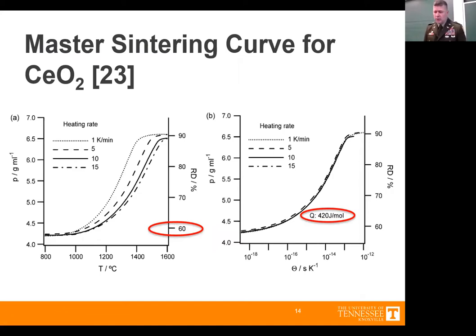There's actually some literature that shows that the master sintering curve method does work reasonably well for cerium dioxide. However, I want to call your attention to two things on this slide, and then we'll compare and contrast those with my own results later. This work starts out at approximately 60% theoretical density. As I mentioned, in industrial processes the powder is poured into some mold or crucible, but then it's either pressed or tapped or vibrated, somehow subjected to an initial densification process prior to sintering, so that all of their sintering curves start out at approximately 60% theoretical density and go up to approximately 90% theoretical density. The other thing is their activation energy is pretty high. Again, it corresponds pretty well with the literature. However, that's not what I found during my research.